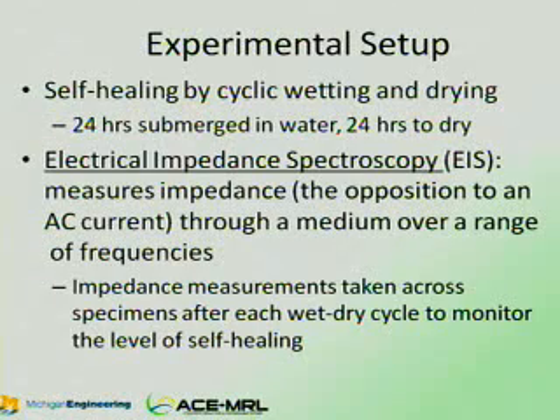Next in my experiment, I will allow the specimens to self-heal through cyclic wetting and drying. My proposed cycle is 24 hours submerged in water and 24 hours to dry. Electrical impedance spectroscopy is the electrical method I will be using to monitor this damage. EIS measures impedance, which is the opposition to an AC current, through a medium over a range of frequencies. These impedance measurements will be taken across the specimens after each wet-dry cycle to monitor the level of self-healing.